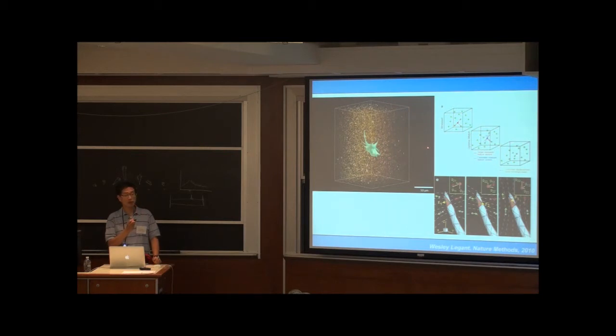Now, the hardest part of this was having this array of beads before the motion and this array of beads after, 2 pictures, and now you got to figure out which bead was which so you can get the strains. And so the way that you do that is you basically take each bead and you ask, where are the positions of all of its neighbors? And so you generate sort of a 3D, kind of like a finite element mesh of where everything is.